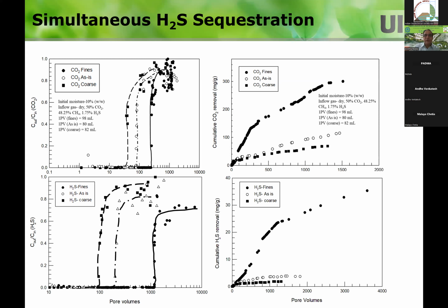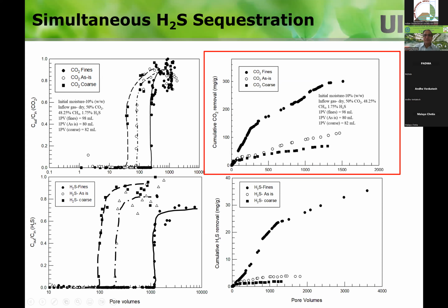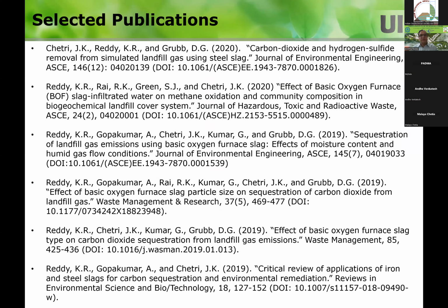And also what we found is that with the slags, finer is better. So the last graph that you see, H2S versus the coarser materials. In fact, that is even better because we are trying to use the fine fraction of the slag anyway. We are getting finer slag anyway. So these are the publications you can see and get more information about it.